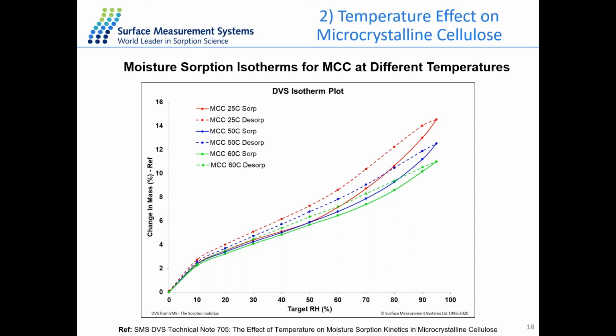So as the temperature increases, the water molecules move more freely out of the box structure, and that will result in a smaller hysteresis gap and an increase in the diffusion constant in the previous slide as well. So there is more energy input, and this will result in the smaller hysteresis gap. So this simple study just demonstrates the effect of temperature on the moisture sorption kinetics at a range of relative humidity conditions within the temperature stability of the material.